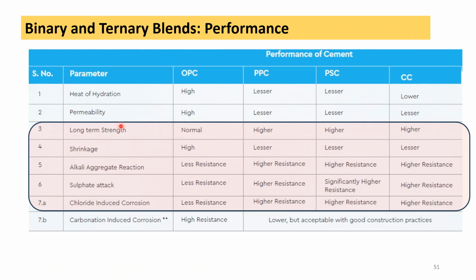So here is a quick summary of different performance indicators. I have ordinary Portland cement. It has a high heat of hydration, high permeability. Of course, I can densify the matrix, but typically, if you look at performance characteristics like shrinkage, OPC has a high shrinkage. It has a lower alkali aggregate reaction resistance, less resistance to sulfate attack, depending upon the sulfate content or the aluminate content. And the resistance to chloride induced corrosion is, if I take that as a benchmark, then with PPC and PSC, I basically score higher on all of these performance indicators.